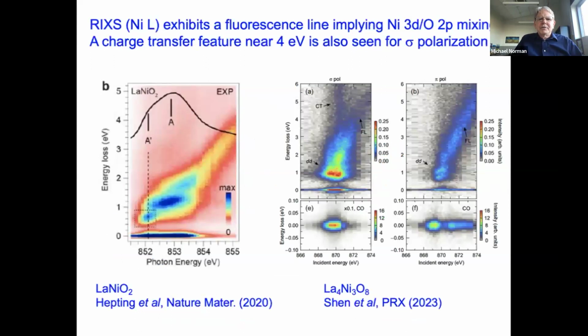You can look at the nickel L edge, and what you see is a nice fluorescence line. A fluorescence line is, if you look at energy loss versus incident energy, you see a diagonal feature in the spectrum. You see a rather pronounced fluorescence line in lanthanum nickel O2. We see this as well in La4Ni3O8, in both sigma and pi polarization geometries. This is a typical signature in transition metal oxides of nickel 3D oxygen 2p mixing. There's also a charge transfer feature that you see in sigma polarization up at around 4 to 5 eV. This is your charge transfer feature.